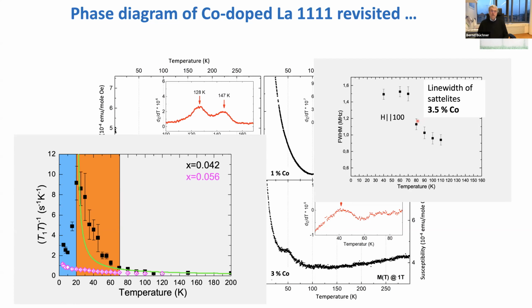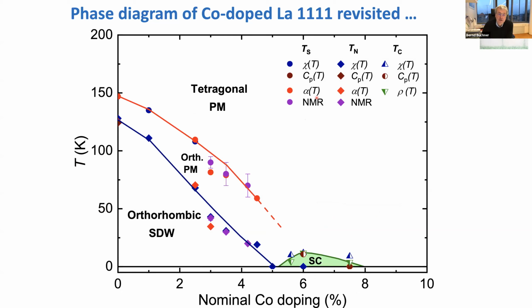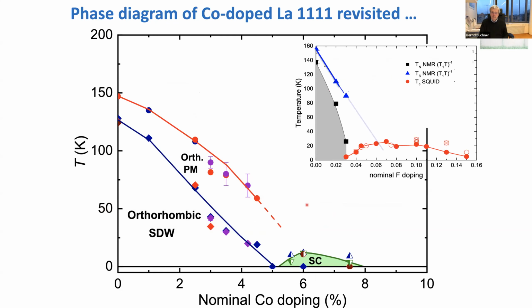So at the end of the day, we end up with the following phase diagram, which shows again the splitting between nematic and magnetic phase transitions, shows decrease. We lose the signatures of the structural phase transition, nematic phase transitions at about 4%. We can follow the magnetism down to these concentrations, and then superconductivity emerges. So that's qualitatively very similar to this phase diagram. Maybe it's a little bit broadened here in this region, but of course we are now discussing compositions in the second digit of the cobalt. So that's the phase diagram, and it's somehow similar to that what we know for the fluorine doping with a suppressed TC due to cobalt impurities.